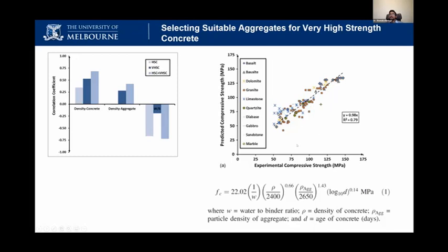And also we can see if you use some types of aggregate, it can reduce the strength. So using the right aggregate is quite important to get the final result. We can actually design a very good binder, even if it is really expensive, but if you don't blend it with the right aggregate, we are not going to get the best out of the binder related to very high strength concrete.